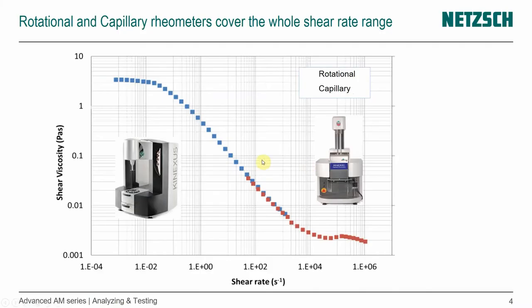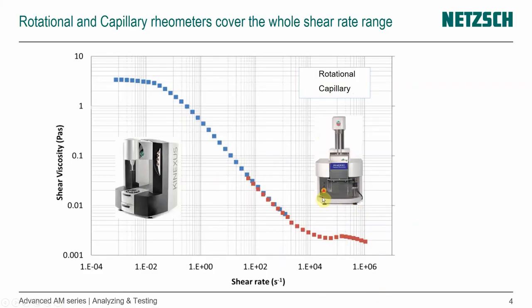And I'll show you in the next episode, not only for extrusion, but for the 3D printing process, what shear rates we actually have. So you can use both technologies to obtain shear rate-dependent viscosity, but the rotational rheometer is really limited when it comes to the higher shear rates. It's more about the molecular mobility. You can also look at viscoelastic properties. And when we want to study the effect of high shear rates, we have to go to the capillary.